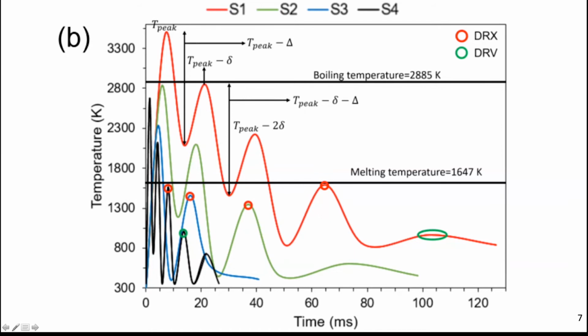And look at the horizontal axis. The horizontal axis is time. I can produce these layers in 80 milliseconds or reduce that time to 20 milliseconds. So that means that the time I need to print the material and to actually make it solid is in the range of tens of milliseconds. When I cast an alloy in industry, an ingot will take sometimes days to cool down. So you can imagine that if I can print with a laser within milliseconds, each of these layers,